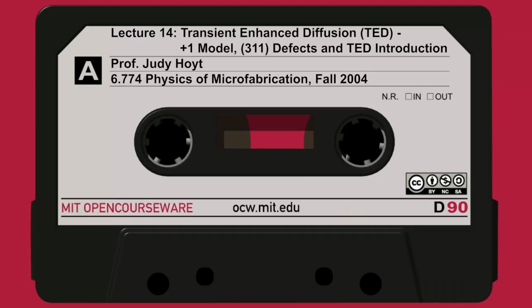And this is, again, review from last time, but I think it's important to review this before we talk about transient enhanced diffusion. Last time we talked about this model with a funny name called the +1 model of implant damage, or +1 model for residual damage. It was published by Giles back in 1991, and the idea was this: what the model says is most of the recoiled silicon interstitials and vacancies recombine very rapidly in the first few milliseconds or hundredths of a second during the implant, or else just when you put it into the anneal.